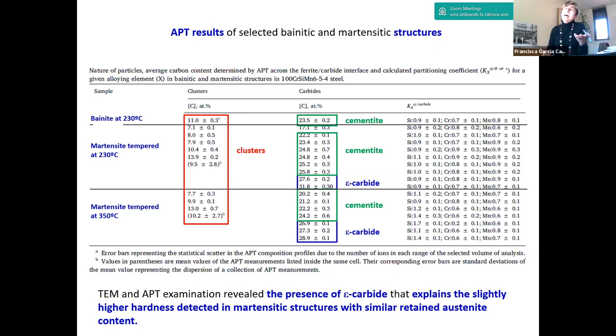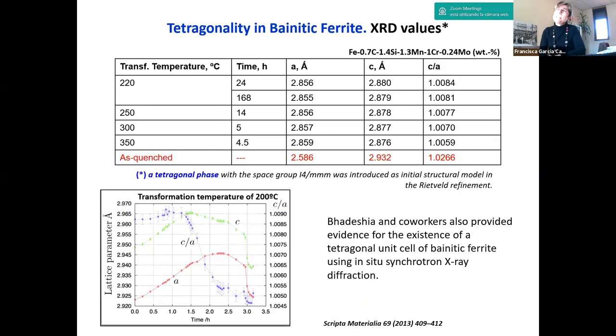What it tells me, apart from the strengthening and everything, is that the evolution of the microstructure to equilibrium is more advanced in a martensitic structure than in a bainitic structure for the same holding temperature. That's the conclusion that I took from here. But let's come back to the tetragonality, which proved to be comparable to tempered martensite, but we didn't mention it more, and that's really interesting. We learned a lot from tetragonality and also from the carbon supersaturation, the metastability of the matrix.